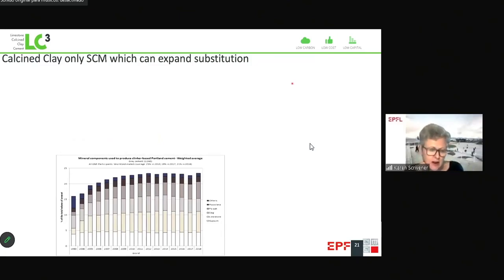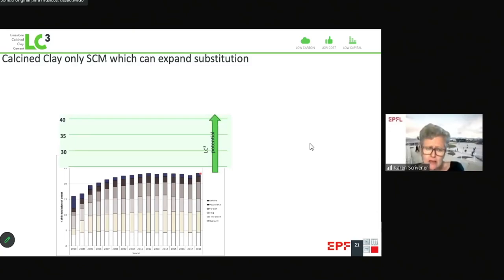This graph here shows the average level of cement substitutions around the world, and this has really stagnated for the last 10, 15 years. And the reason it's stagnated is because of this shortage in the availability of slag and fly ash. So if we remove this shortage coming from just using slag and fly ash, and we bring calcined clay into the equation, I think we could quite easily increase the substitution level to about 40%, and this would represent saving about 400 million tons of CO2 per year.